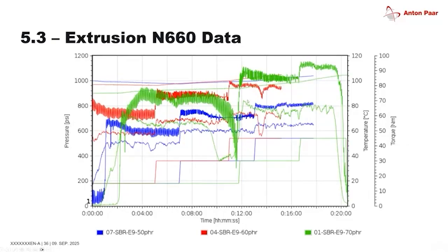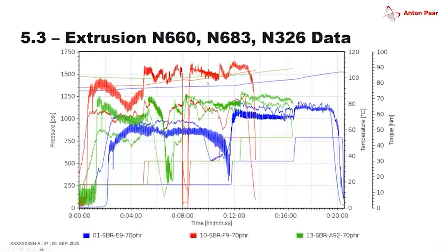But we quickly recovered because there was probably the strip running out and not fed accurately. The important part is that you see a tendency where it's stable and with less jitter. But the higher we went, and of course here the top curves are the load. So we see, because of some discrepancy, the 70 PHR was the highest lubricated one, while the others were a little rougher.